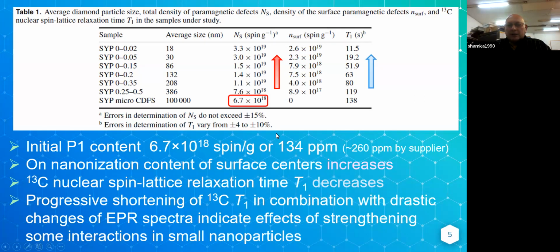Okay, let's summarize this data. Initial P1 content corresponds to 134 ppm. The manufacturer shows 260, 2 times larger, but it was measured by optical spectroscopy and it's not precise. This is more or less a precise number. When you do crushing and separation, the content of surface centers increases. It's logical. It's mechanical defects which are located on the surface and within the interface layers.